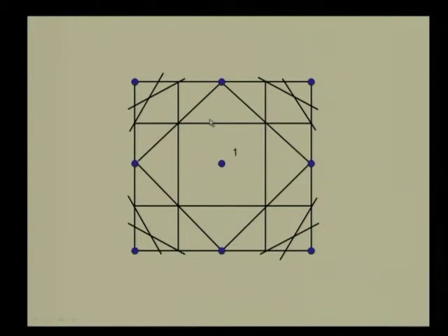If you cross one Bragg plane, but you do not cross a second Bragg plane, then that region is a second Brillouin zone. We find around this point several locations where this is true. So, this is one region where this is true, you have crossed one Bragg plane to get into this region, but you have not crossed further Bragg planes, right, and all these perpendicular bisectors are the Bragg planes by the definition that we have given them. So, we crossed one Bragg plane, we did not cross the second Bragg plane, so this belongs to the second Brillouin zone, but there is another region here which also belongs to the second Brillouin zone for exactly the same definition because it fits the same definition. This is another such region and this is another such region. So, taken together we have 4 locations where we identify the second Brillouin zone. So, those are the second Brillouin zone.